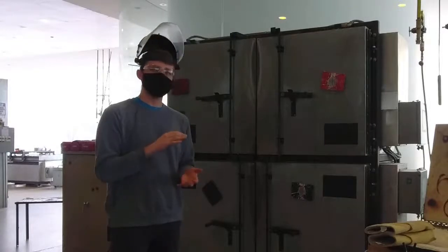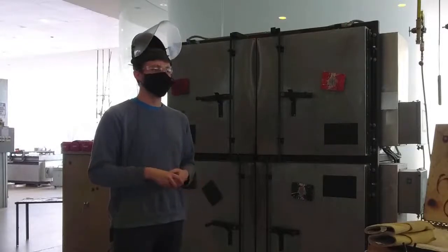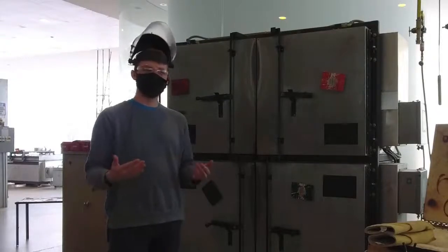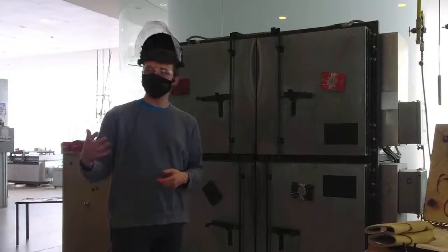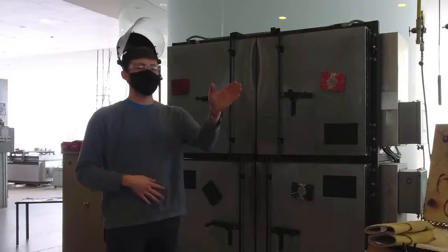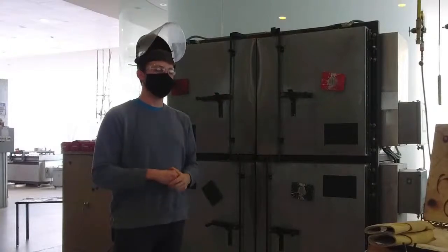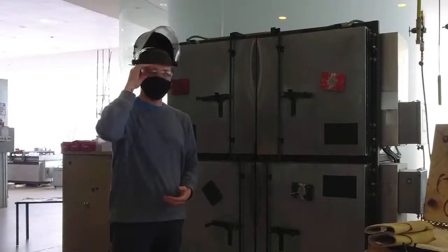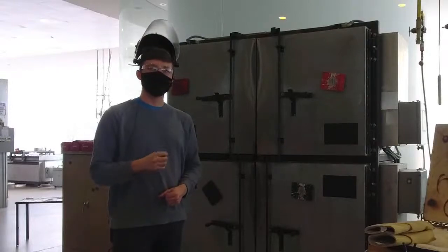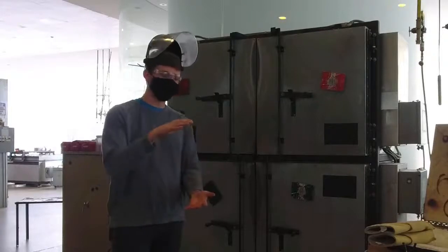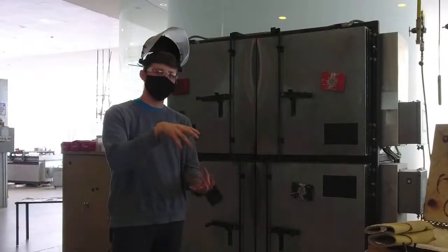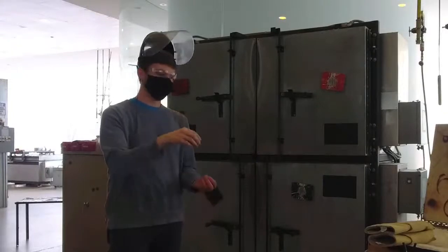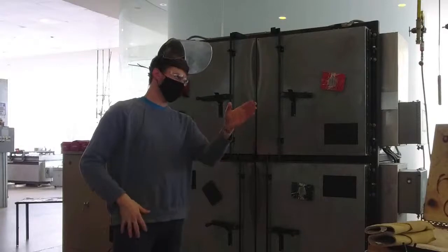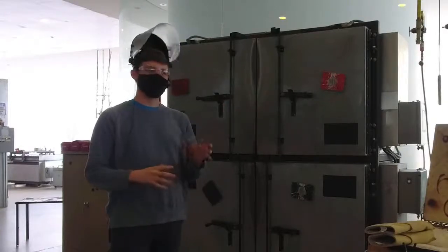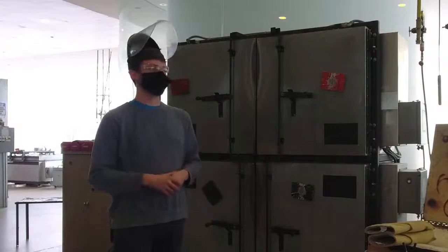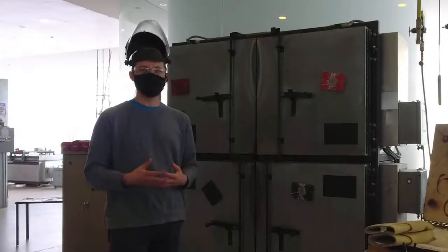But the thicker the glass gets, the longer the annealing process. So for those that are familiar with our collection here at the museum, or if you're not, you should definitely come in and check out our big glass bench in our ancient gallery. That bench is about maybe 3.5 foot thick. It's very, very thick. And that piece had to anneal for 11 months to fully cool it, just because that thickness needs to disperse from the center all the way, pushing the stress out of the material to the surface. So it's just a really amazing thing to kind of see and understand how glass works and just how the material behaves under certain circumstances.